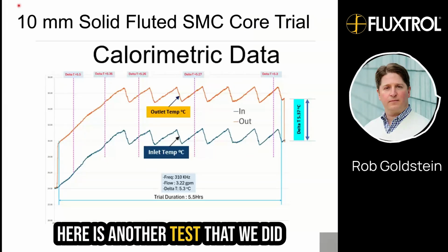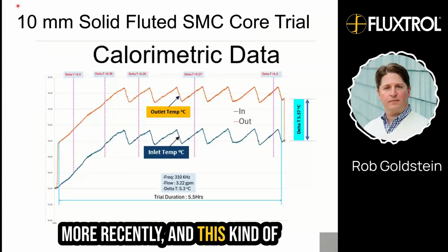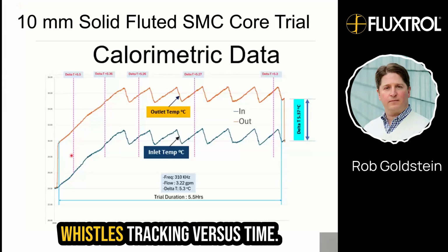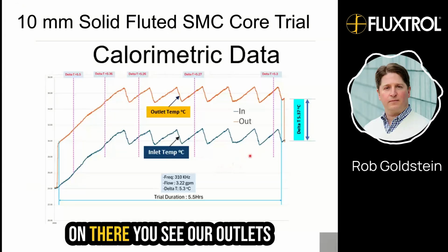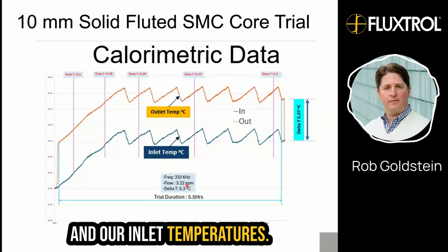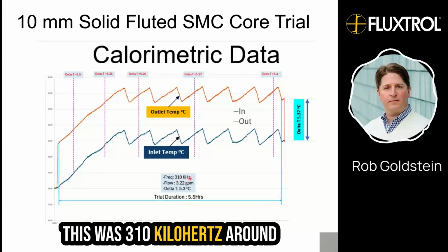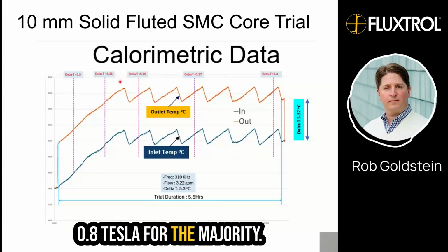Here is another test that we did more recently, and this kind of includes all the bells and whistles, tracking versus time, and with the closed loop chiller on there. You see our outlet and our inlet temperatures. This was 310 kilohertz, around 0.8 Tesla for the majority.